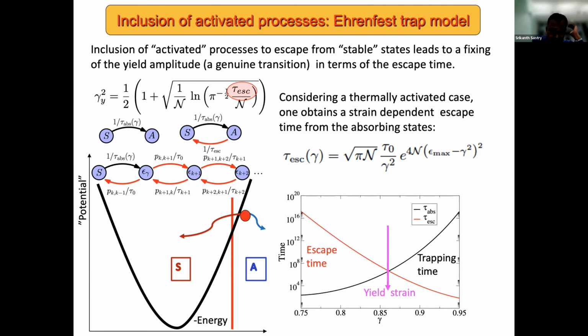And if one puts in this possibility of an escape and with a characteristic escape time, one can redo this calculation and one finds that the yield amplitude now is really properly fixed, not by the observation time, but by the escape time. Okay, and one can go a little bit further and ask for what the escape time would be if one considers not only transitions between the yielded and the absorbing states and the reverse at a given rate given by the inverse of an escape time, but one considers the entire spectrum of states that are below and allows for transitions between them.